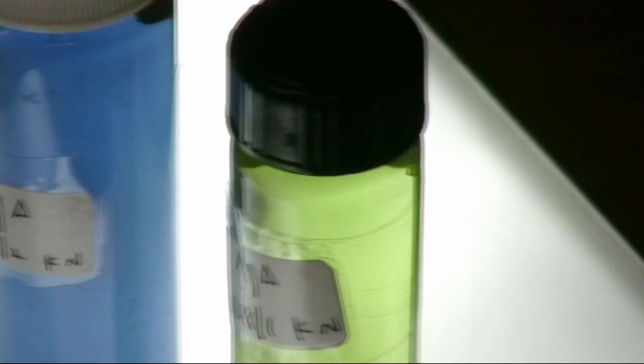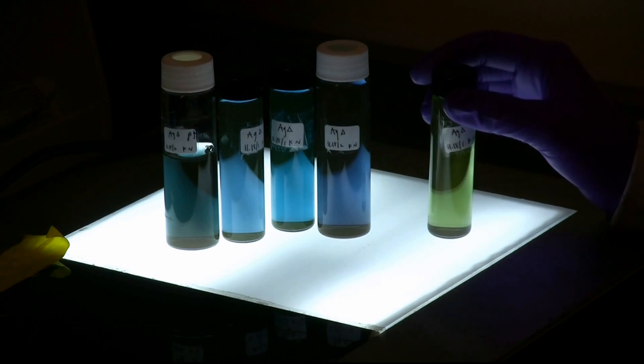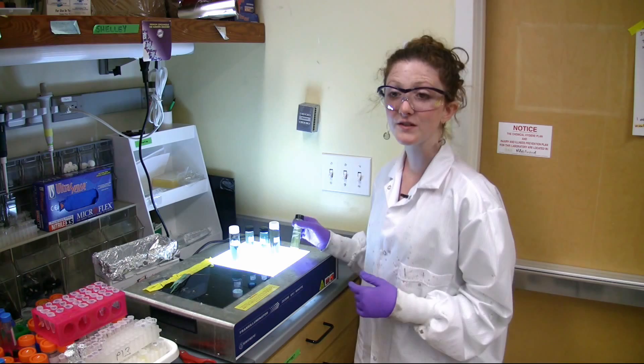Being left in the ambient fluorescent light of the laboratory for about two or three weeks, the silver seeds turn these colors. This bottle right here is a good example of a solution that's probably mostly silver nanoprisms — flat triangular platelets. This bottle is in transition: some particles are spherical, some are prisms, and it reflects that mixture in its color. The pointed parts of these triangles soften over time, like rocks in a river losing their sharp edges, and as they soften they change into discs as opposed to triangular platelets, which corresponds to a color change.